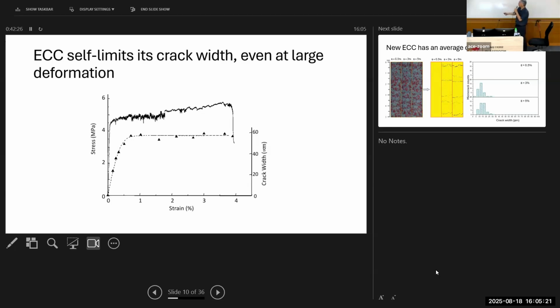And you can see that as I strain the material in tension, pulling the specimen in tension, going up to 1% strain, which is very, very large compared to normal concrete when it fractures at 0.01%. So it's 100 times that. And the width of the microcrack increases up to about 50 or 60 microns on this axis. And then remarkably, look what happened. After that 1%, when you continue to strain the specimen, even up to 4%, the microcrack width maintains more or less constant at less than 60 micron.